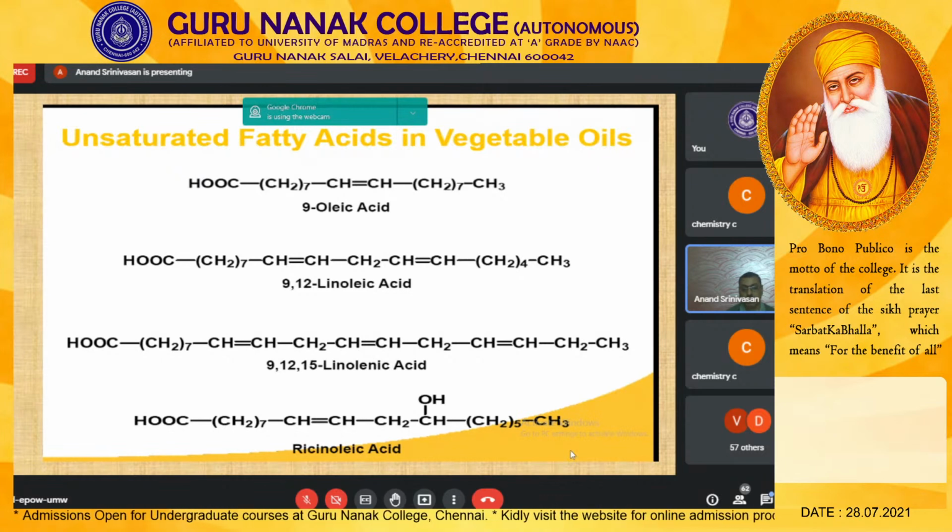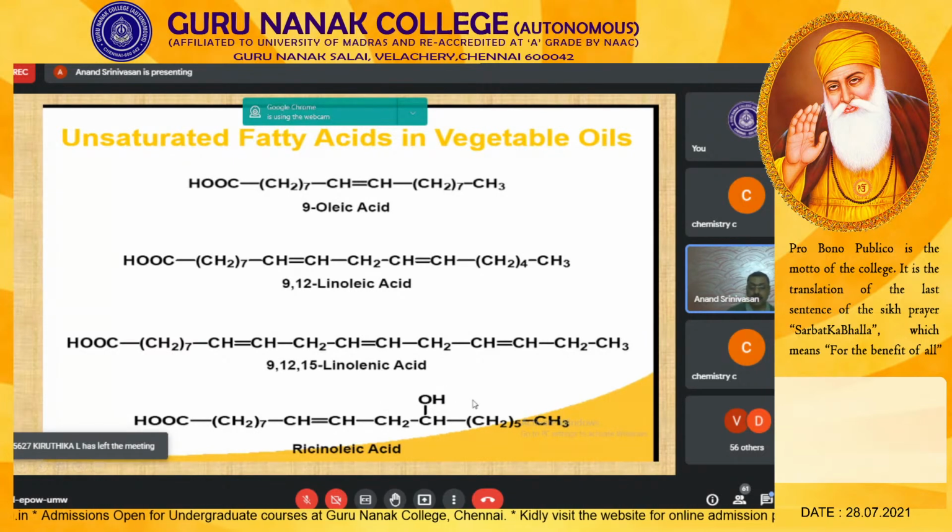In fact, one of my students did a project on ricinoleic acid based polyurethane. This OH group is made to react with the NCO. So you can get polyurethane from ricinoleic acid, which he combined with polylactic acid and made a wonderful film for packaging application. There are plenty of chemistries possible as far as saturated and unsaturated fatty acids are concerned.